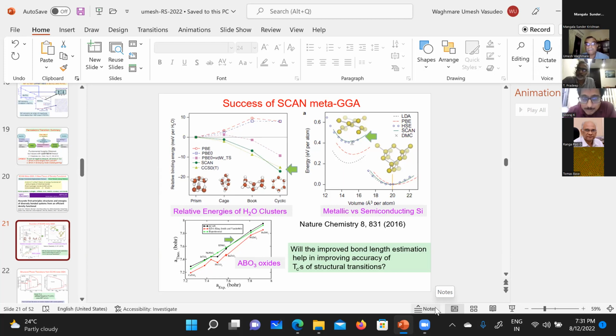So we have also employed the SCAN functional for the metal oxides, and we found that they reproduce the experimental structural parameters like lattice parameters quite well. I'm not aware of how accurate it will be in terms of the energy. For example, the one which you showed has a very low energy barrier for the transitions. How good will it be on the energy barrier side?